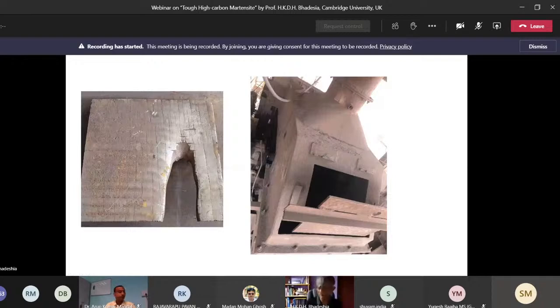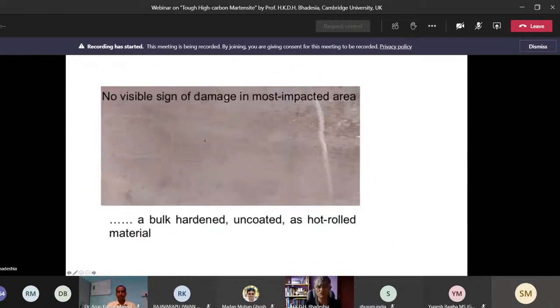So we replaced this with our new steel, and it has been in position for approximately, I'm guessing now, approximately 18 months since it was installed, and there is no visible sign of damage. There's no hard-facing alloy put onto this. So we are examining here the most impacted area, and nothing has happened. So we now need to simply leave it in position until some sort of damage happens before I can completely claim success on this. But everything looks promising, okay? And I believe that the steel has now been installed in other locations where there's different kind of wear in the Tata Steel production plant in Jamshedpur.